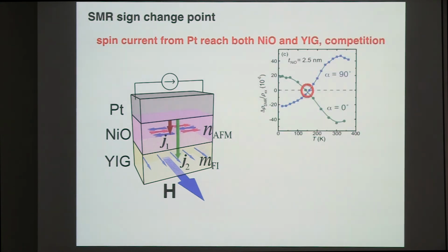So if you look at the temperature at which you have the sign change, it means that the SMR is 0. What is actually happening here is a competition of the SMR due to YIG, because now you have finite spin transmission, so YIG will automatically give you a positive SMR. But the nickel oxide is still below the Néel temperature, so it tends to give a negative SMR. So in the end, one positive and one negative, they will cancel out somewhere.